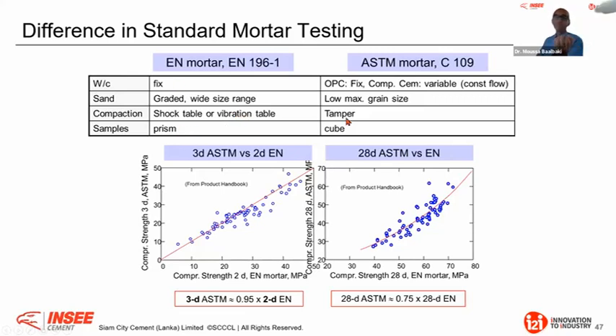In the ASTM, it's different. For OPC, it's fixed, water cement ratio 0.485. For blended cement, it is variable because you achieve a certain flow. It is not a fixed water cement ratio. After that, for the sand, they have a monograin sand called sand of Ottawa, very fine sand. Okay, they use a tamper manually to compact, and they use cubes.